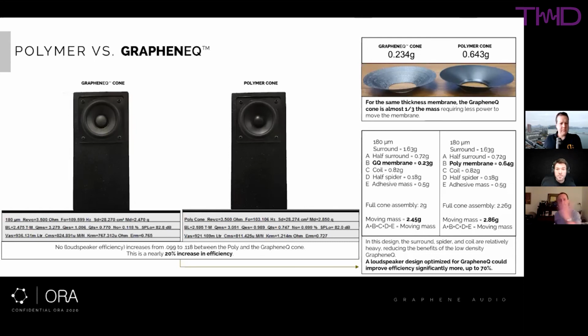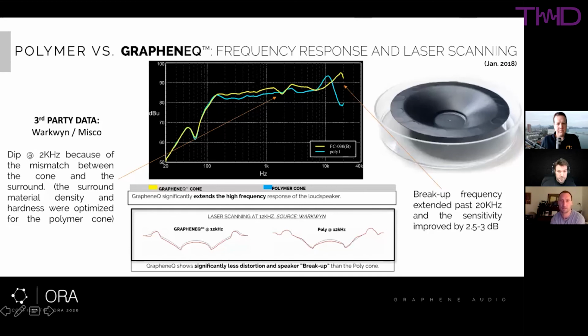We took the driver cone, we ripped it out, we made the exact replica in graphene with the same geometry, the same thickness, same everything, and just popped it back in the same speaker. It's not a particularly good loudspeaker to begin with, but we can see the performance delta is interesting. The first thing you can notice is that the graphene membrane is almost a third of the mass of the original polymer cone. And even when you add in all the other masses, we still have enough of a mass savings overall that we see almost 2.5 to 3 dB increase in level across the bandwidth relative to that original polymer cone.